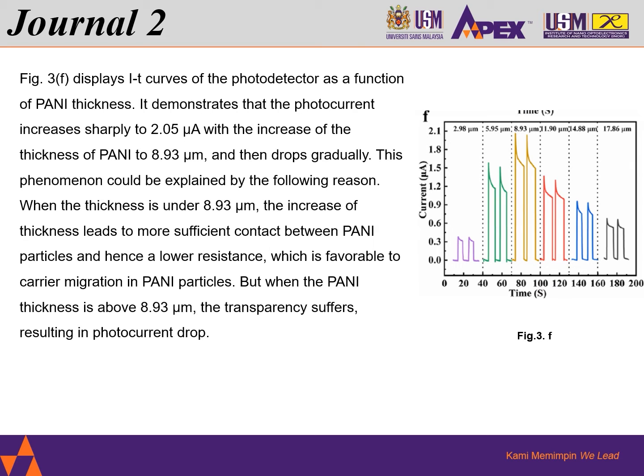Now figure 3f displays I-T curves of the photodetector as a function of PANI thickness. It demonstrates that the photocurrent increases sharply to 2.05 microampere with the increase of thickness of PANI to 8.93 micrometer and then drops gradually. This phenomenon could be explained by the following reason.